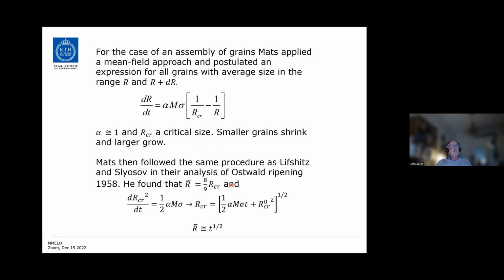Then he considered an assembly of different grains, and he applied a mean field approach and postulated an expression for all grains with an average size between R and R plus dr. And it looks like this. So alpha is a numerical constant, approximated as unity, mobility, and grain boundary energy. And this is the grain size in this size class, and this is the critical size. So grains which are smaller would then shrink, and grains which are bigger would grow.